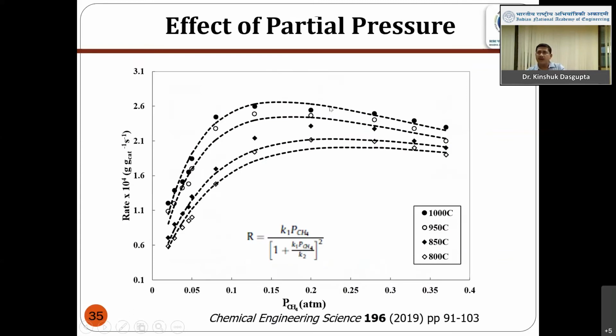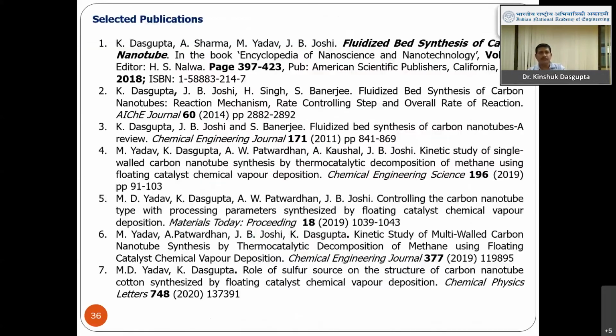Now we studied the effect of partial pressure on the synthesis rate of single wall carbon nanotube. Here it is slightly different. In case of multi-wall, the curve was increasing with a decreasing slope. But here, after some partial pressure, there is a decrease in the rate of synthesis, because it follows a different rate law. That is why single wall carbon nanotubes are generally produced at a low partial pressure of hydrocarbon, and we cannot produce single wall nanotube at as high a rate as multi-wall carbon nanotube. So the synthesis rate of single wall carbon nanotube will always be lower than that of multi-wall carbon nanotube. We could do some publications on that.